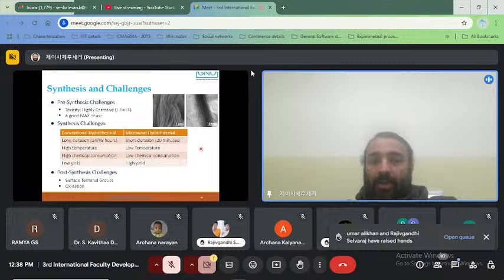What is the problem? The conventional hydrothermal method we use for the exfoliation takes almost 48 hours. Sometimes it may take more than 48 hours, and it may not exfoliate. High temperature is required, high chemical consumption is required, and also we get a low yield. Once we centrifuge and dry it, we get very little material.